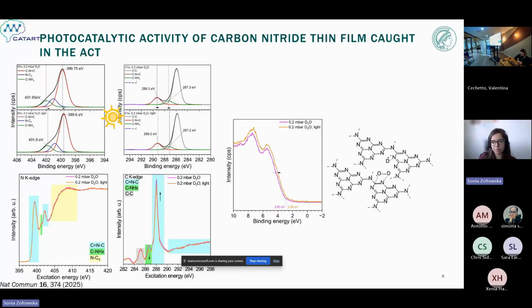On the other hand, it must be noticed that we don't see significant differences in the nitrogen K-edge subspectra. Actually, the most significant change is observed in the carbon K-edge restricted area, and probably shows us the pivotal role of this particular feature in this photocatalytic step.